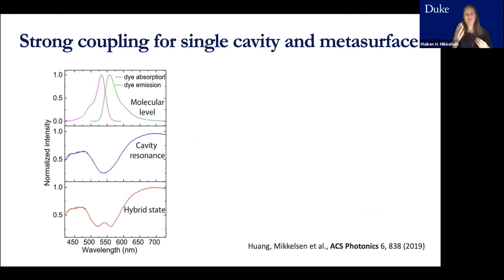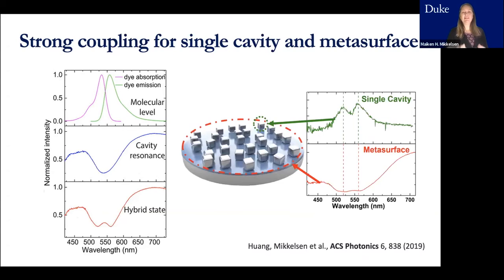When that interaction rate is faster than the decay channels in the system, we are seeing this hybrid state. This is characterized by a double peak or double dip in the cavity resonance spectrum, sometimes in the fluorescence as well. And what is neat here is that we see this both from the single cavity structure as well as from a large area surface.